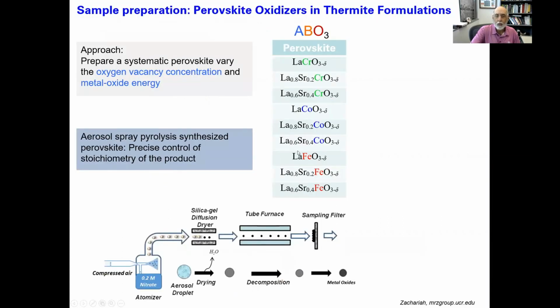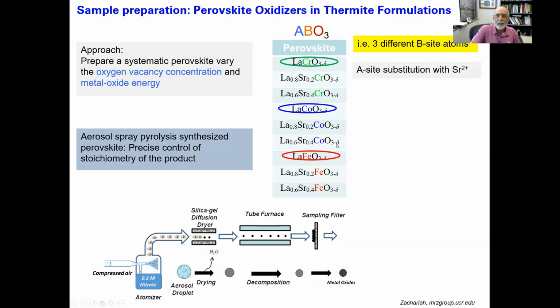So we're going to make a large range of perovskite systems by aerosol growth. The details are not important, but they're all lanthanum, strontium based, but then I'm going to dope them with either chromium or cobalt or iron. And the reason for doing this is the following. So I'm going to have 3 different B site atoms. This is the chromium, the cobalt, and the iron. So the A site substitution, which is normally lanthanum, I'm going to substitute with strontium.